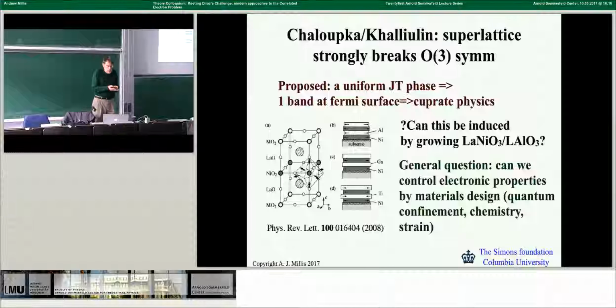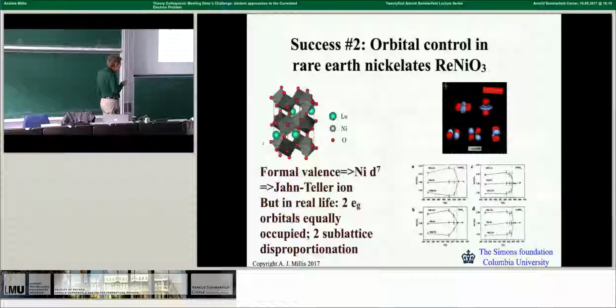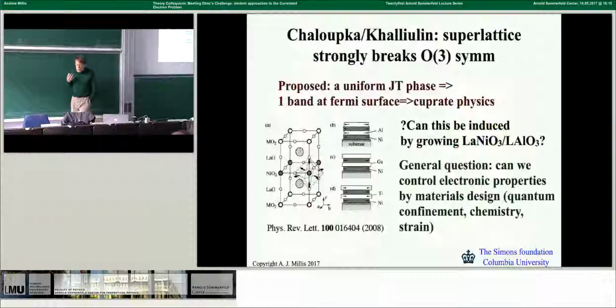All right? He then argued that this symmetry breaking can be used to control the orbital occupancy, so that instead of having these 2 orbitals equally occupied, you'll only have this one occupied. And that's interesting because having only one of the 2 d orbitals occupied is the thing which is empirically crucial to getting high transition temperature superconductivity in the copper oxide materials. So what was proposed is that you make this superlattice, you completely lift the orbital degeneracy of the d orbitals, and you get something whose electronic structure should be favorable to high Tc superconductivity. So that's the proposal.